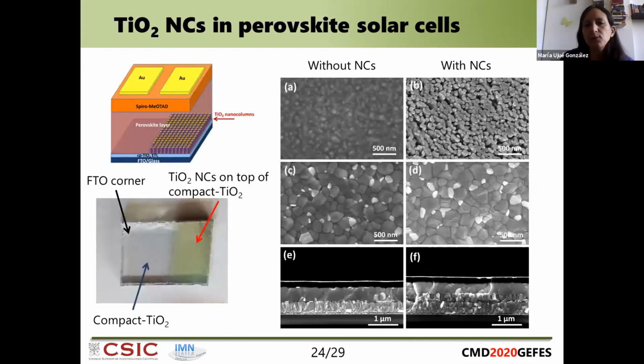In order to have a fair comparison and to have the solar cells in the same conditions all the time, on the same substrate half of the cell had the regular structure with a compact titanium layer and perovskite, and in the other half we deposited the titanium and then oxidized it to titanium dioxide nanocolumns. On top of this, we fabricated two solar cells. The first thing was to check that the quality of the perovskite on top of the compact titania or the nanostructured titania was the same. And as you can see here, yes, we can get a good quality crystalline perovskite in the two cases.